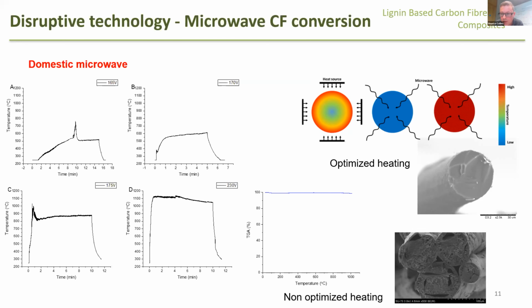Not only do we produce the carbon fiber with low carbon emissions associated with it, but we were able to produce the carbon fiber in a matter of seconds. We did mechanical testing, and we compared the carbon fiber produced using conventional ovens with the carbon fiber that we produced using the microwave, and they retained their mechanical properties after microwave production. This is something that we really want to take further. We optimized heating. In the first trials we got a lot of porosity because we had not optimized the heating, but once we started to optimize the heating, we were able to achieve fibers without pores, and that's why we were able to get really good mechanical properties.